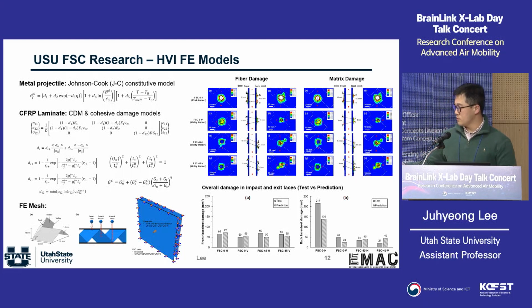And then if you're looking at the bottom right side, these two bar graphs compare the numerical prediction versus the actual measurement on the impact side and back side. So even though this model is relatively simple, you see the prediction and test results are quite compatible with each other. What that means is, by doing more tuning, the model prediction can be close to the actual behavior. That means we can save at least $1,000 per shot.